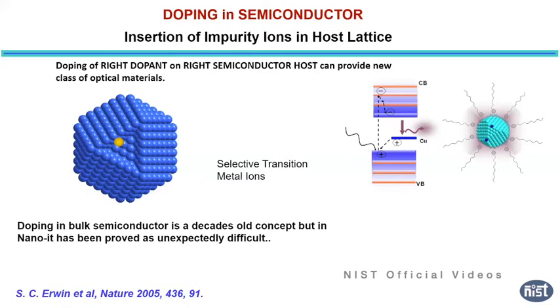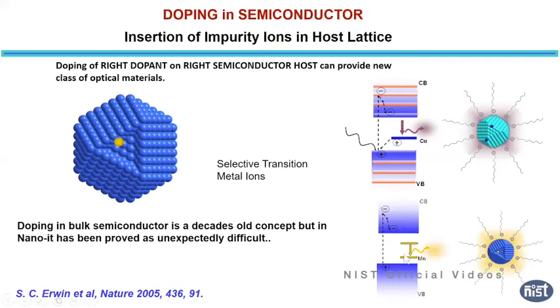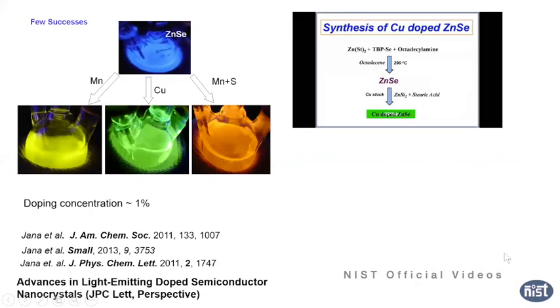It depends on many properties of the transition metal ions. And also manganese has a different band diagram. So the exciton transfers to the manganese part, and you will see the orange emission from that. I will show you some images of nanocrystals, like zinc selenide. Under UV in the dark it's blue. When you put in manganese, you will see very bright orange emission, and with copper, it's very bright green emission. And if you put in manganese and sulfur, because it shifts to the red, it's yellow and dark orange emission.